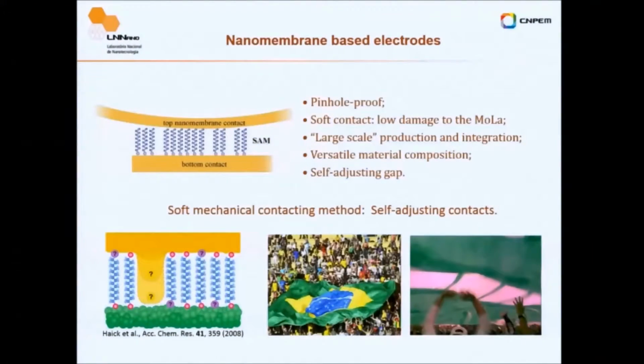The problem is that you never know exactly how many molecules you are contacting. But actually, nobody knows that. Even if you make a deposition, you have to make the assumption that you have an ideal area. So we have a soft contact, first because it's low temperature, because you roll in liquid, so room temperature contact. Large scale, I showed, because in our device, you can have 100 devices on a chip. It is more than you can really measure or characterize. You can have a versatile composition, since I can change the material on my tube. I can do basically any combination, respecting the selection rules of the rolling process. And it's a self-adjusting gap. First I put a molecule, then I put the contact. Not really a lateral gap, where you make a gap and then you hope that you can bridge your molecule. So it's a soft mechanical and self-adjusting contact.